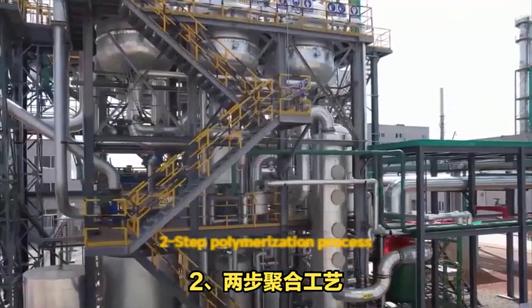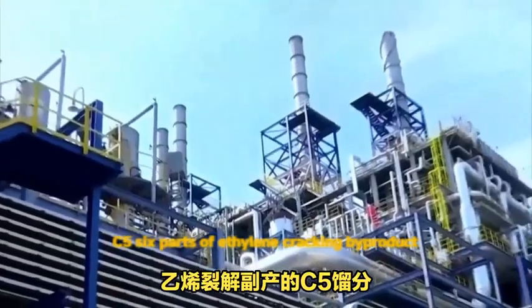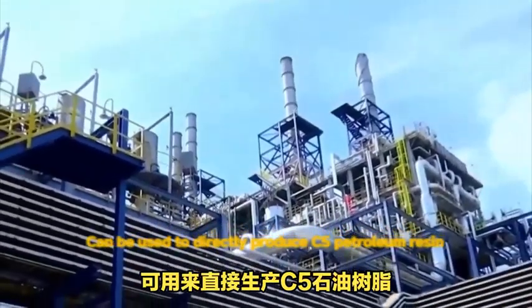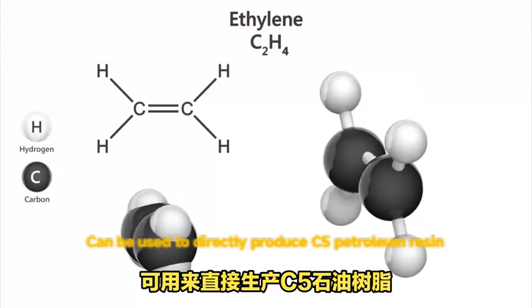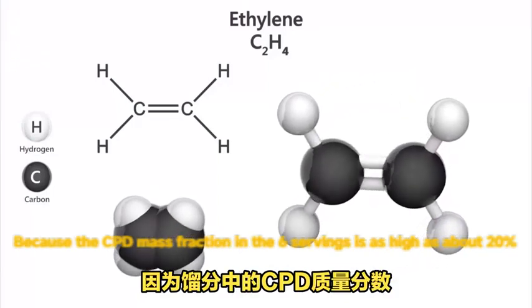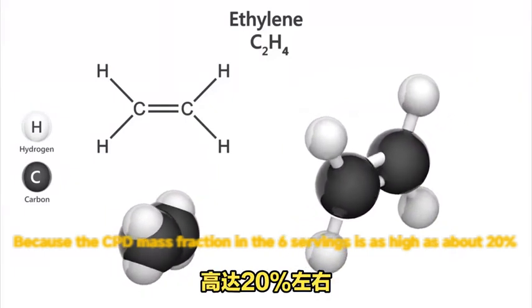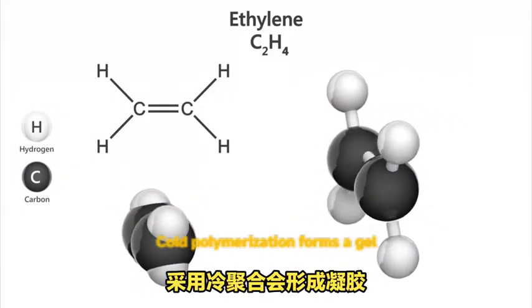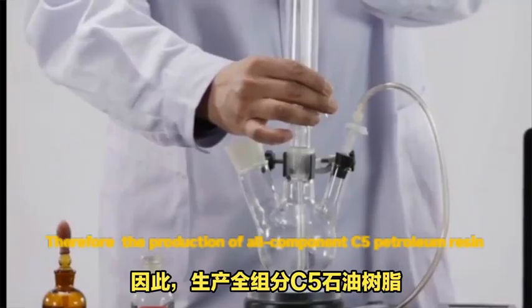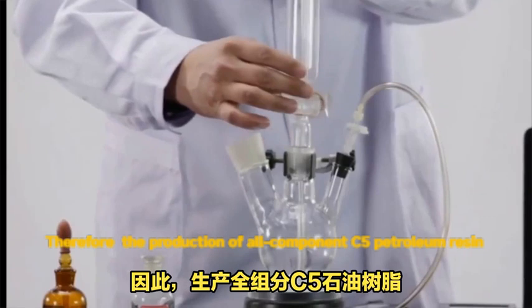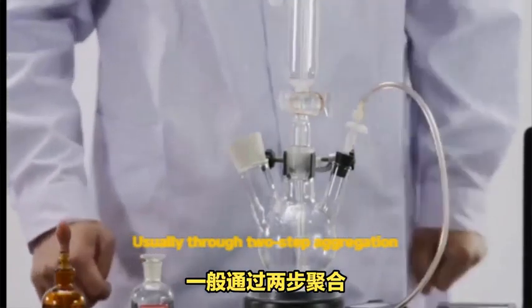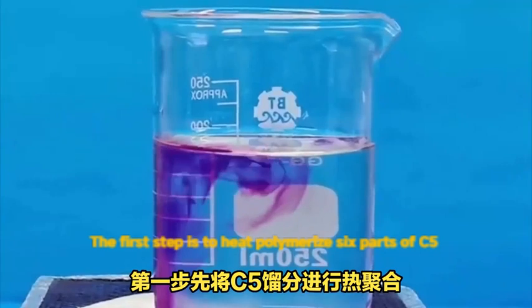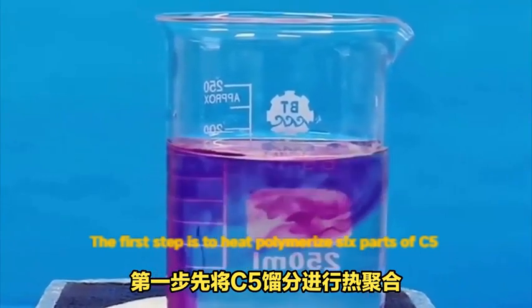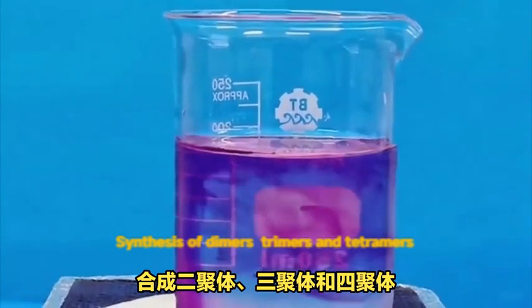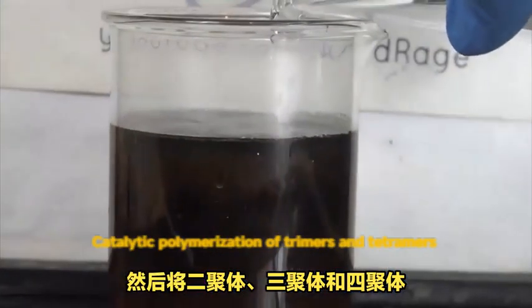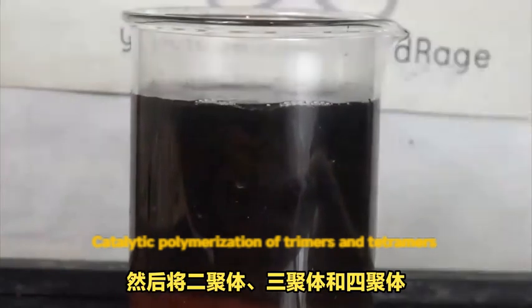Two-step polymerization process. The C5 fraction, a byproduct of ethylene cracking, cannot be used directly to produce C5 petroleum resin because the CPD mass fraction in the fraction is as high as about 20%, and cold polymerization forms a gel. Therefore, the production of whole-fraction C5 petroleum resin usually goes through two-step polymerization. The first step is to thermally polymerize the C5 fraction, synthesizing dimers, trimers, and tetramers. Then the dimers, trimers, and tetramers undergo catalytic polymerization.